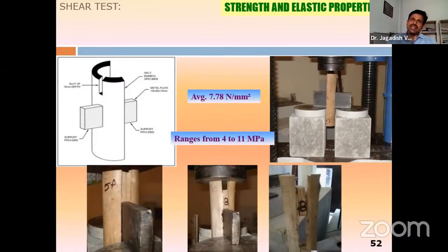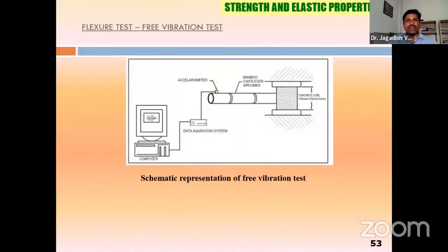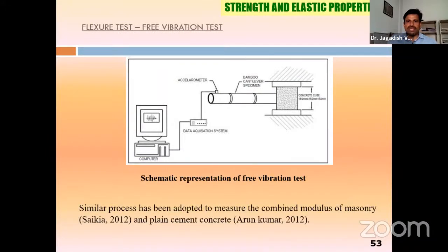You can see the average is coming around 7.7 and the range is between 4 to 11. It all depends on the wall thickness of the bamboo too. We can also find out the modulus of elasticity using a simple free vibration test.